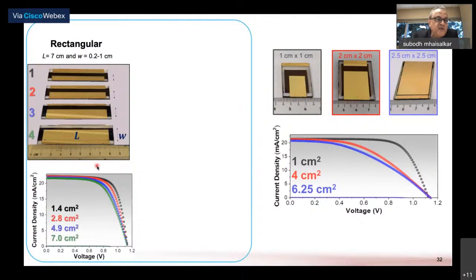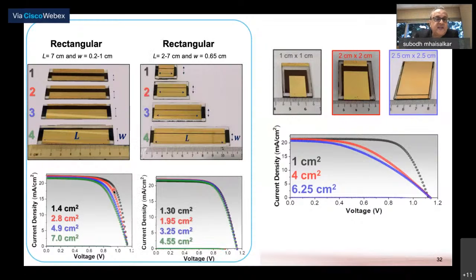In the first experiment, we essentially held the length of the stripes constant, and we varied the width of each of these stripes. What we observed is that if the stripe width is in the range of 0.2 to 1 centimeters, you really do not have very significant changes in terms of the fill factor. So in the next study, we fixed the width of this device to 0.65 centimeters, and we varied the length. As you can see, for this fixed width, there really wasn't a very large difference in terms of the fill factor as you go from a shorter length to a longer length. These studies really helped us define the design rules in terms of stripe sizes that we will make into modules, which I'm sharing in the subsequent slides.